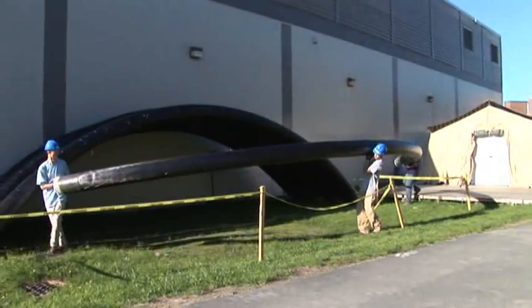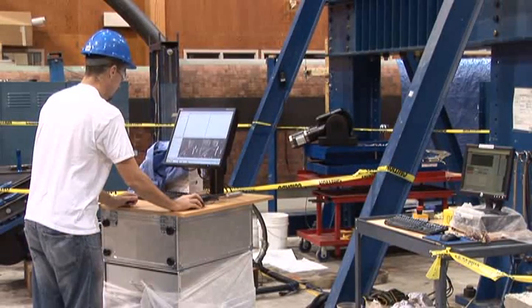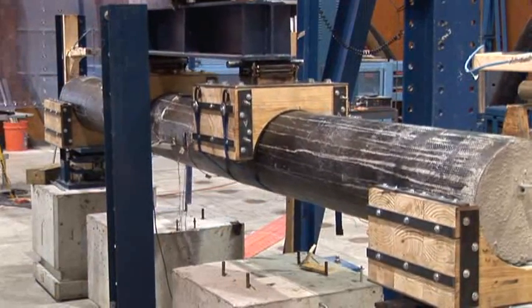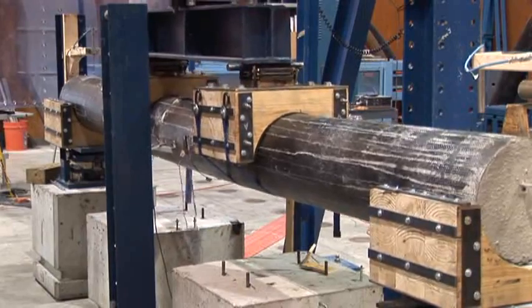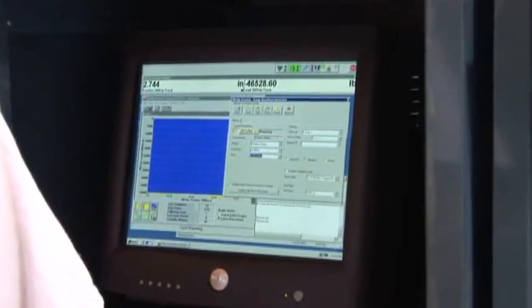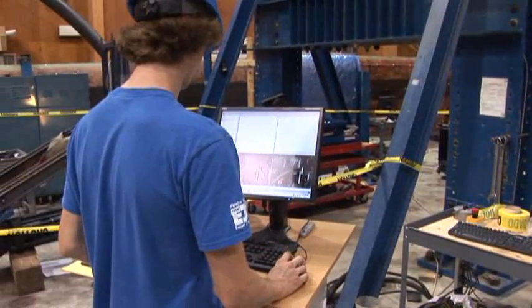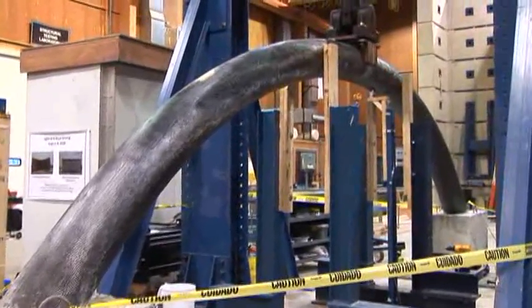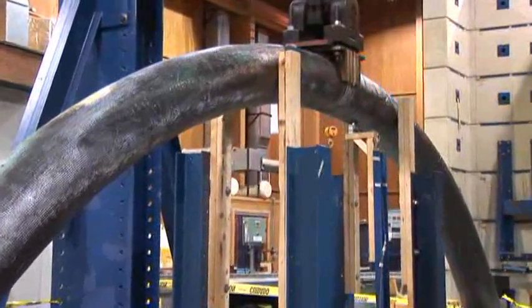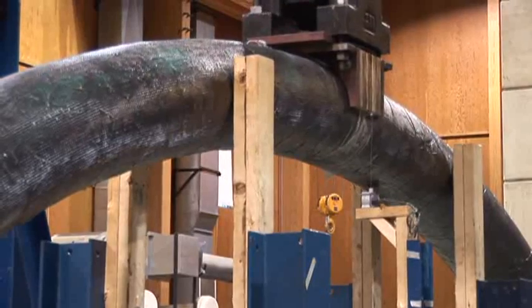These features have been tested in the lab. During the accelerated fatigue testing, concrete-filled arches were subjected to the equivalent of 50 years of truck traffic over an interstate highway bridge. Results showed that the arches retained their full capacity after fatigue tests were completed, proving that the residual strength of the arches was equivalent to the initial strength. Moreover, testing has shown that the arches are extremely ductile compared to conventional reinforced concrete, forming three plastic hinges and maintaining peak loading during strength testing.